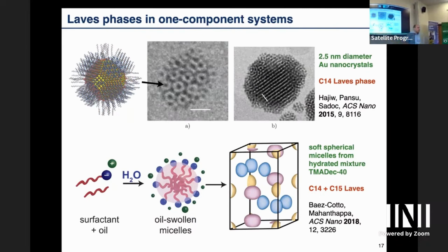And these spheres can also form crystals, just like you can get from colloids. But what is a bit different from the colloids is that now this is a very dynamic object. You have these surfactants and they form spheres. The surfactant can leave a micelle and go to another micelle. So here's an experimental image where they did tomography, also getting a C14, C15 Laves phase. And what they see is something they call dynamic dispersity. So you start out with, if these micelles are all far apart, they all have roughly the same size. But then when you crystallize, what happens is that some of the micelles can grow at the expense of the other micelles, and you can develop such a binary crystal just by mass transport in the sample. And this is also known in alloys.